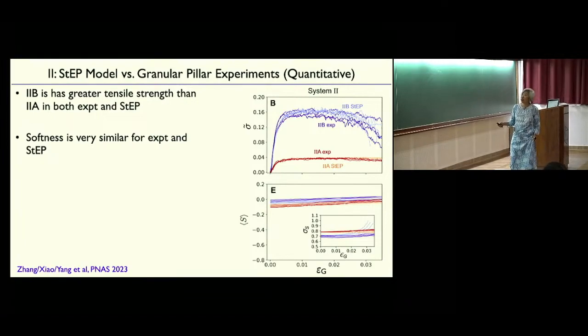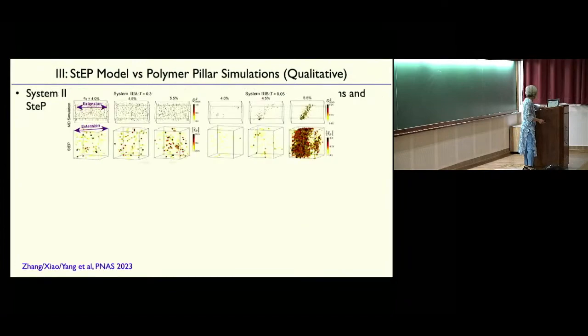The step model is the light red, and the experiment for the small particles is dark red, and for the larger particles, the experiment is dark blue, and the simulations are the light blue. And again, very good agreement for average softness and standard deviation of softness. Okay, I'm going to leave out this.